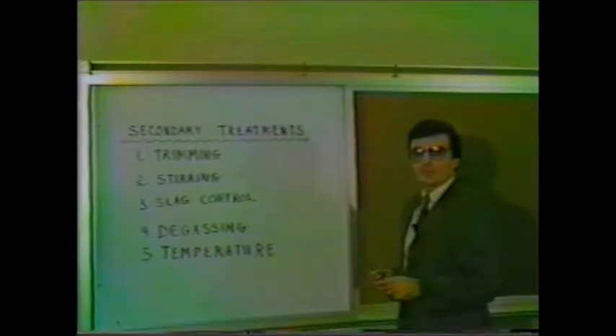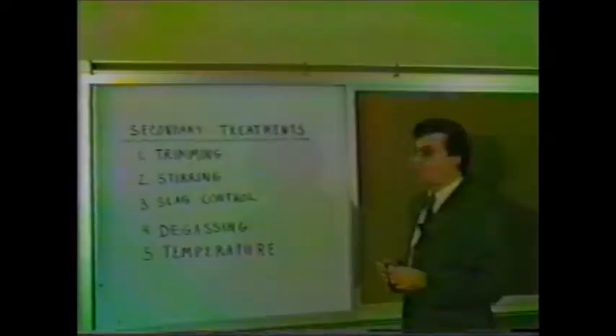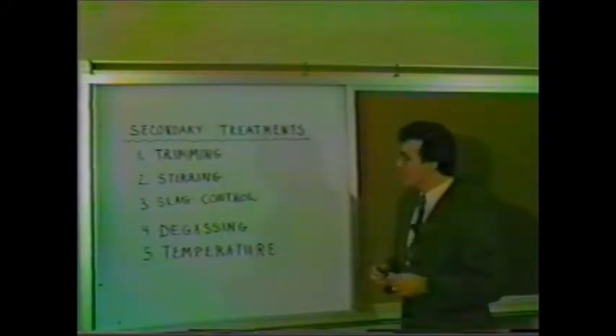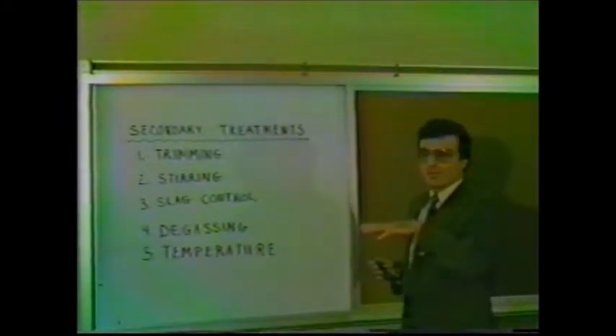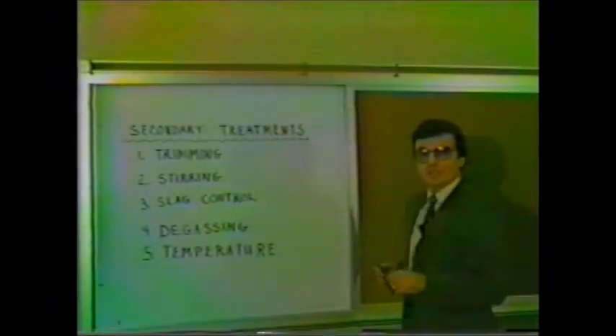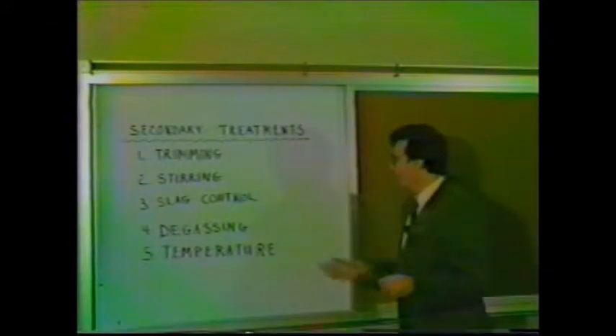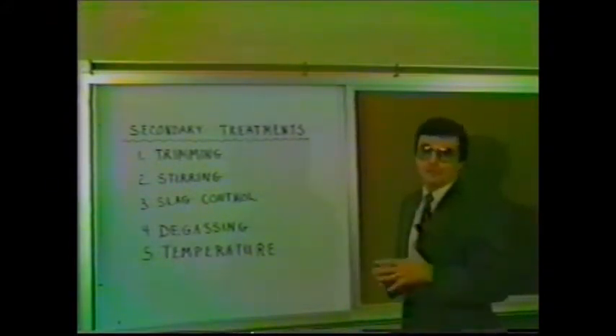The third thing you can do is control the slag, and by controlling the slag, you can do things such as skimming the excessive slag, and by doing that, it would promote a cleaner steel. You can also degas the steel by pulling a vacuum on the steel, and what that does is pull out the dissolved gases prior to solidifying, and the reduction of these gases will also result in a cleaner steel. And the last thing you can do is control the temperature with electric arc heating. The purpose of this is to put the steel at the correct temperature and at the correct time when you're just ready to cast it, so it's most optimum for solidifying.